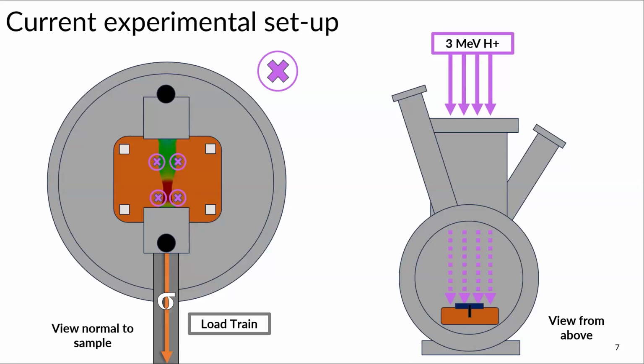So I irradiate normal to my sample surface, and then I do a preheat of my sample for 16 to 18 hours beforehand so that my thermocouples and the rest of the chamber can come to temperature, because we can't actually weld anything to the sample or else we're introducing defects. So temperature measurement is kind of difficult. But we do a preheat, and then we calibrate our IR camera, which we then use to track the temperature throughout the rest of the experiment.